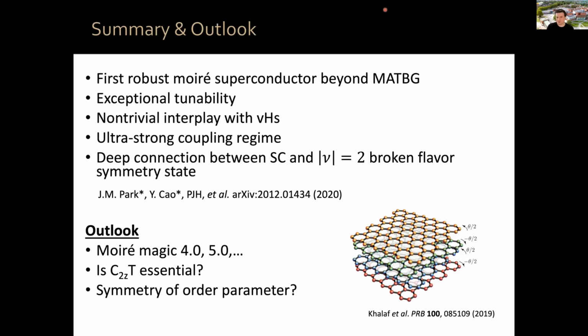I think it would be an interesting experiment. In the magic angle twisted bilayer graphene case, several groups have reported in-plane field measurements. In our original paper, we seem to have a little bit of Pauli limit violation, like 20%, but you're defining critical temperature at 50%, so we couldn't say whether there is really a substantial violation of the Pauli limit. Then in subsequent work, we realized that the in-plane critical field is anisotropic. We didn't have enough field to test the largest axis of the ellipses, so we saw this nematicity, and for the largest axis it seems like we may violate Pauli by a bit more, but we didn't have enough field with our vector magnet to actually check this.